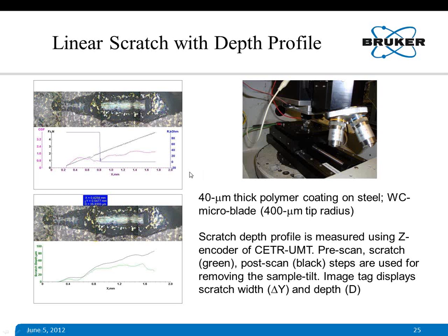During such a scratch test, we can also perform a scratch depth profile, which is shown in the bottom figure here. What we do in this case is a pre-scan to know the surface of the coated specimen. There may be a tilt, so we want to evaluate that, and then we do the progressive load scratching, and then a post-scan to measure how much elastic deformation there was and what is the permanent deformation after the scratching. And you see on the bottom it shows those two numbers.